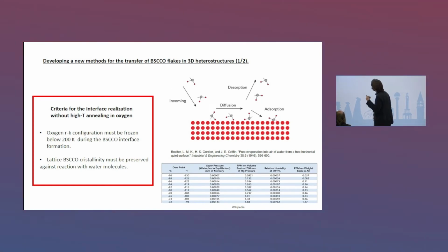So then we needed to develop a new method to transfer this material, because the oxygen configuration, we know, must be frozen below 200 Kelvin; above that the oxygens are mobile, so to preserve the ordering. And as well, we needed to preserve the lattice, like the incommensurate lattice modulation, from interaction with any sort of water molecule. Because in any possible situation, even at high vacuum, you will have water molecules that will come and diffuse on top of your surface. We are talking here about surface science, okay?